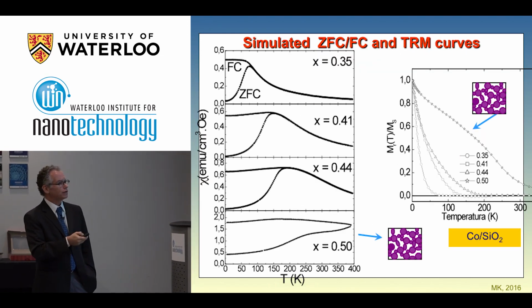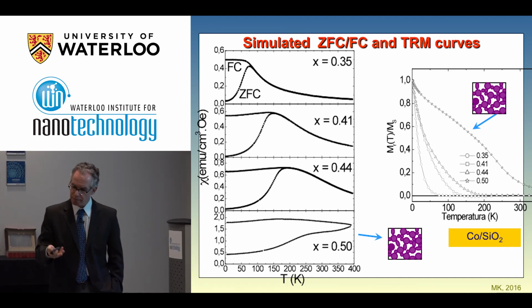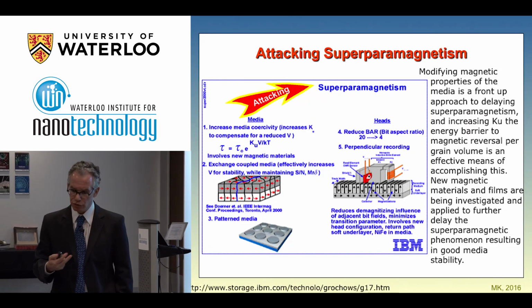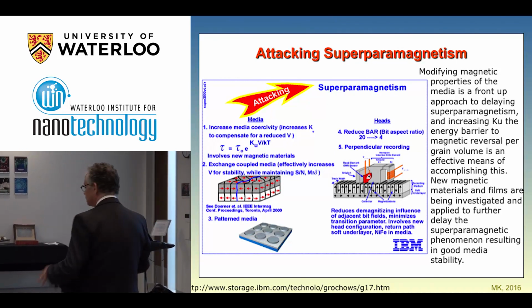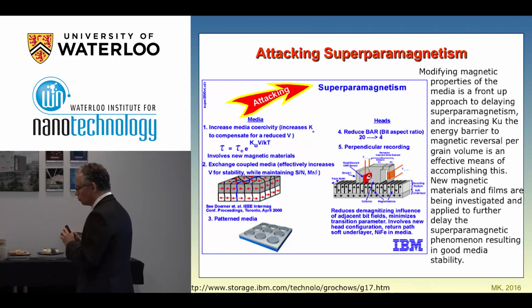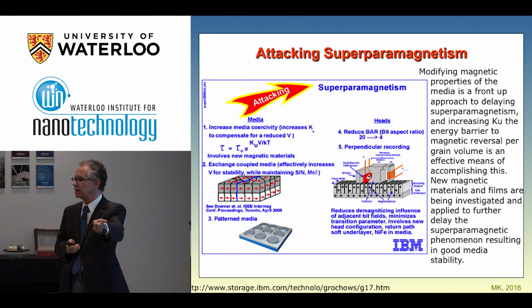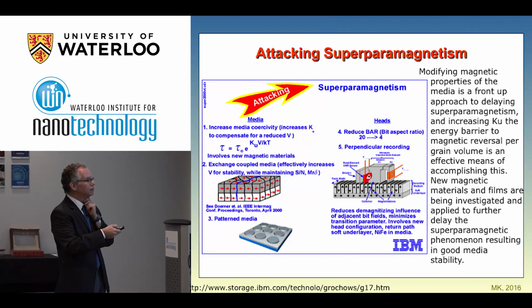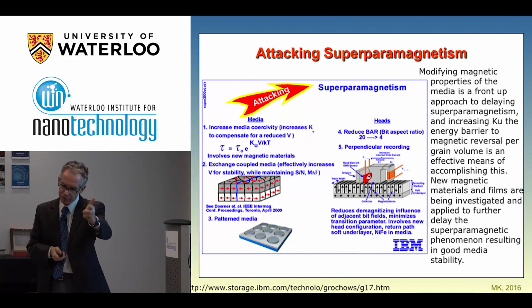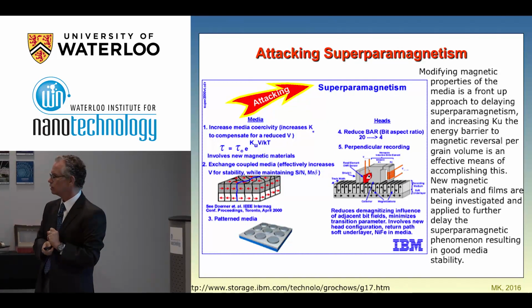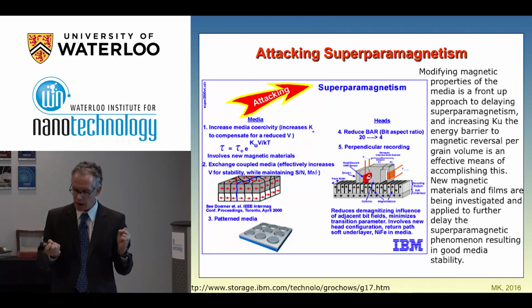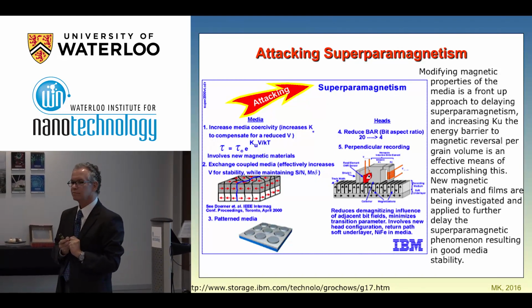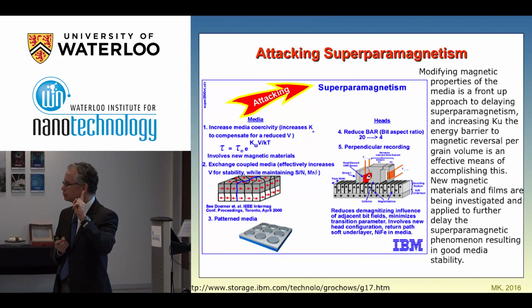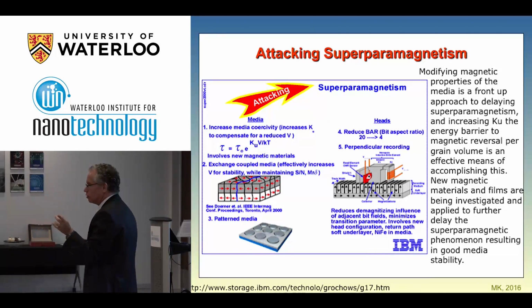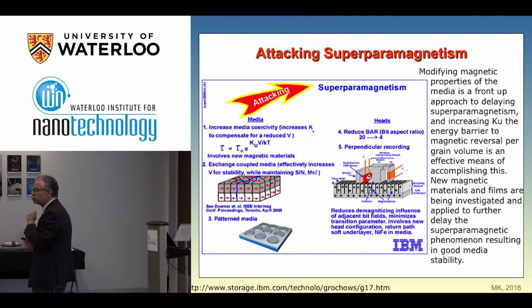So this was just to mention that ideally what you need is to have a nanoparticle or a magnetic system, just to come back to the problem of the magnetic recording industry, a magnetic media or a magnetic bit which would have a strong stability over time. So there are many approaches that were tried. The first one was to increase the anisotropy of the system. Why not use, for example, hard magnets to make a hard disk? So it will become extremely difficult to make the magnetic moment change direction.